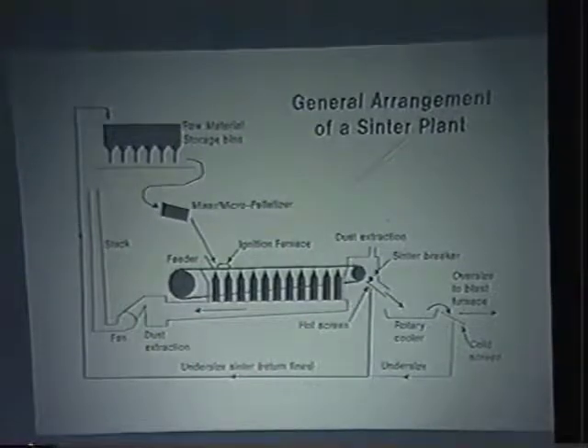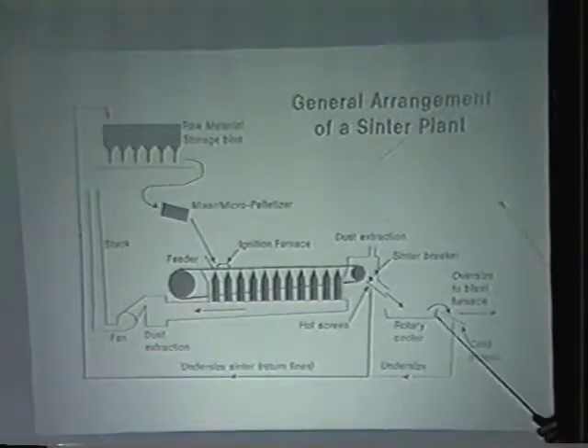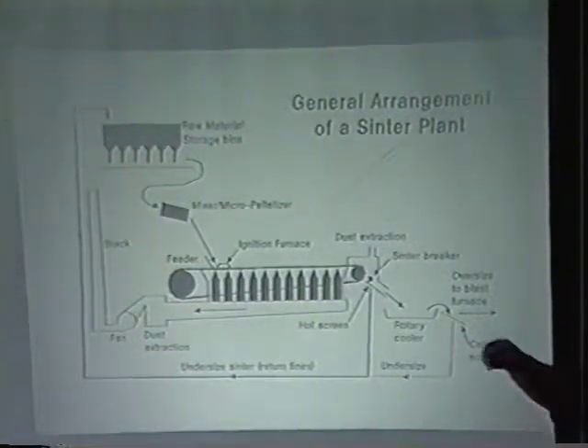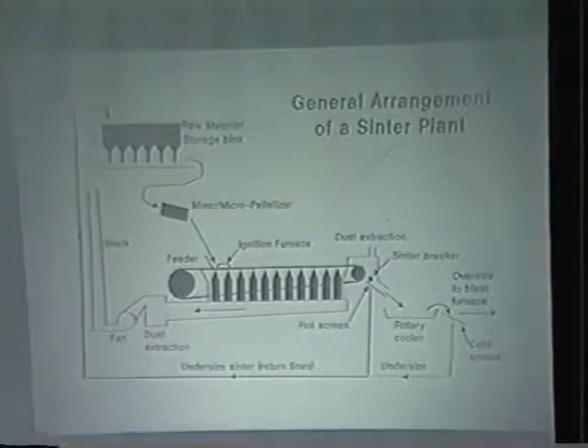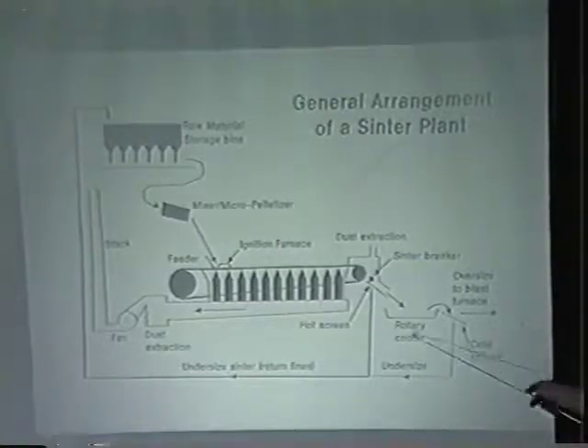We screen it to about minus 3/16 and plus 3/16. And then what is greater than plus 3/16, we put on a big rotating cooler. We have to cool this material because it comes off the sinter strand at about 2,700 degrees Fahrenheit. It's pretty hot. And then when we cool it, we screen it again for plus 1/4 inch, then we screen it for plus 3/16 to feed to the furnace. So I got my numbers a little bit messed up. But we screen it again, and then that's another part of the blast furnace burden.